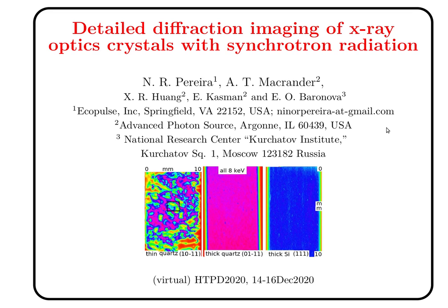You see here on the first page already what we want to bring forth, namely on the left side is a reflection, X-ray reflection at 8 keV from a flat thin crystal as might be bent in an X-ray microscope. Usually these are spherically bent, and you see the reflection is very ratty. In the middle and the right side you see the reflection from, as it should be, namely completely uniform across the surface, from quartz as is the left side as well, and from silicon.